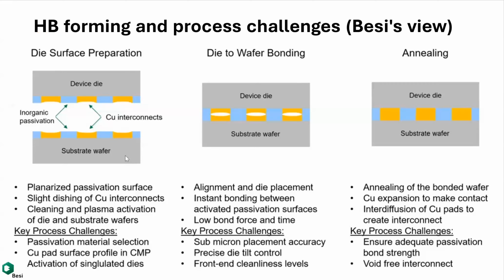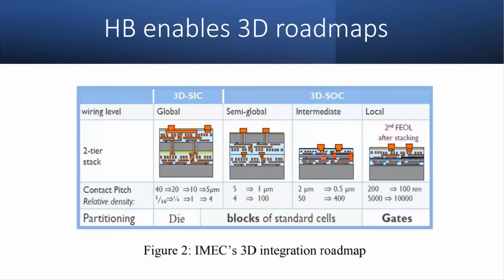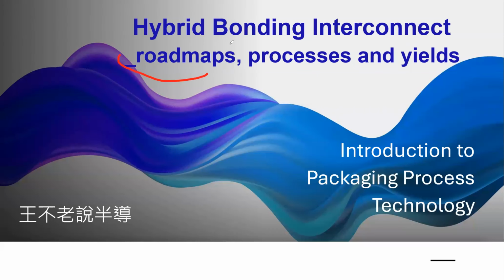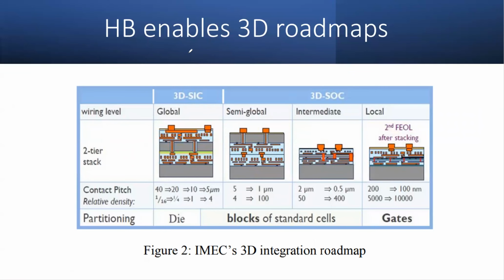Let's now look at more in a grand scale. As I introduced today, I'm going to talk about many roadmaps, process, and yield. Let's look at the roadmaps. The hybrid bonding from this IMEC 3D integration roadmap is pretty clear. Right? So the key is to look at the contact pitch. The more advanced you go, the scaling, you go from, say, a couple of microns. Let's start to see the hybrid bonding already. Anything below 10, you start to see that happening. Of course, you could use the solder bonding to below 10. That's possible. That's still possible.